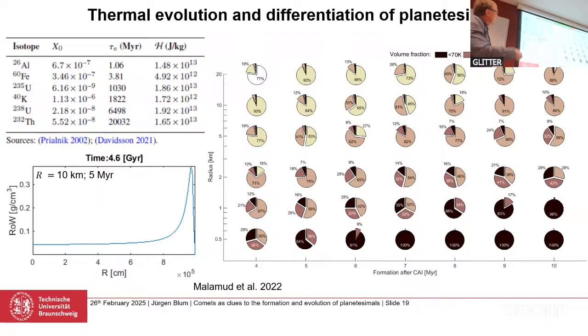Here are the half-lives or decay times, and the abundances, and then the energy release. And as one example, for a planetesimal of 10-kilometer radius that was formed 5 million years after CAI, because the formation time is important here. As we form earlier, the inheritance of radioactive nuclei is bigger. If we form later, they have already decayed before they are incorporated into a planetesimal. So in this one example, we show the water abundance. Here, the original water abundance was 0.1 in these units. And after the decay has happened, we have reduced the water abundance by more than half in the inner 8 kilometers out of the 10. And all the water has been deposited just short of the radius, because the outer radius is cold again.